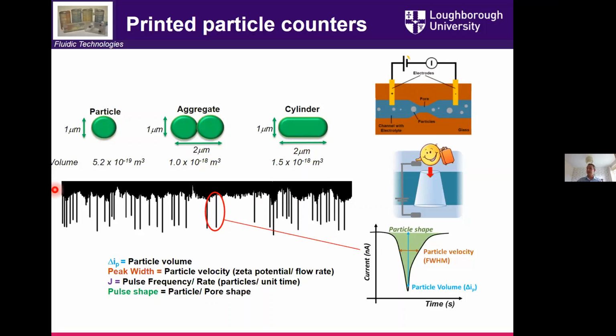And so what you're looking at here is a baseline current that you would expect to see between these two. And every single one of these pulses is a particle that passes through a sensing zone in a microfluidic chip. And those pulses, as in the example of the optical case, tell you something about the droplet or particle that goes through. It tells you something about the particle volume, and it's very sensitive to particle volume.